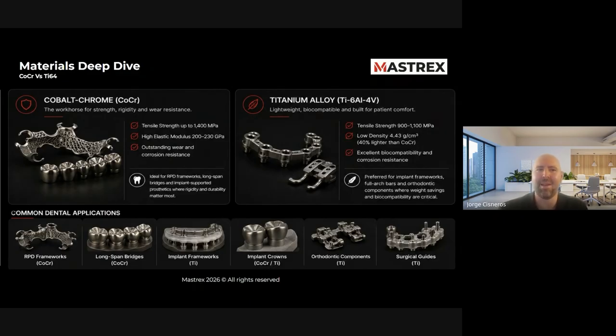However, for my time in the industry, the one thing that I have noticed is the price has come down. There are a lot of powder producers out there, and they're starting to come up with new ways of producing the powder. The traditional way was what's called gas atomization. You heat up the material to a liquid, spray it through a nozzle, let it air cool, and then filter out the particle size you want. And it's nice. You get a very round particle as a result, which helps with that spreadability, as I talked about. It just can be a little bit more expensive.